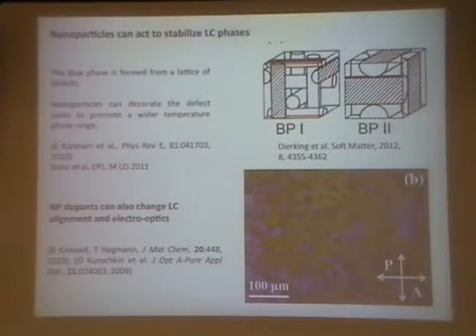Okay, so to introduce the talk, I think I just want to point out a couple of interesting things that have been done recently with putting nanoparticles in liquid crystal to show how this can be a powerful application. And one of the most interesting things that we've found is that when we put very small particles in liquid crystal, I'm talking about particles as small as the liquid crystal molecules themselves, very small, a few nanometers, what do they tend to do? Well, there's been a lot of work looking at how they like to go to defects in liquid crystal phase. The nanoparticle does not necessarily behave like the liquid crystal is a good solvent for it, and so they'd like to go to areas where we have low ordering, say where the defects might be.